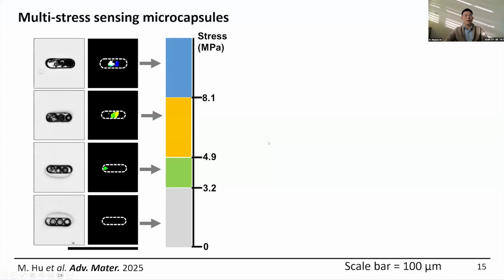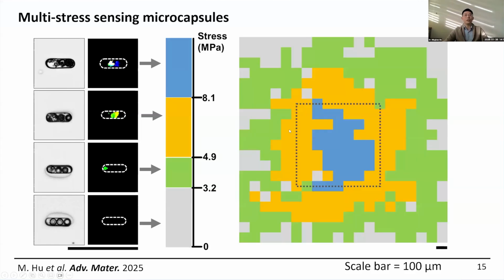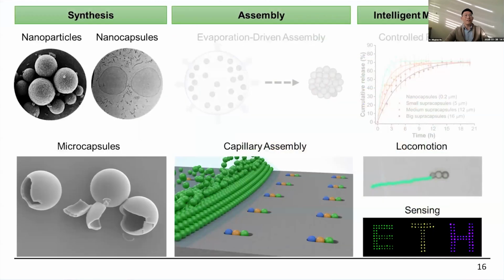Then we further apply a higher force to the PDMS film. With that, we translate this fluorescent signal into this color map. We can nicely see this gradient color, which shows the different stress precisely on this broken PDMS film. So here we showed that we can use the nanoparticle or nanocapsule synthesis, the microcapsule and nanocapsule, while with the capillary assembly we realize the sensing functions.